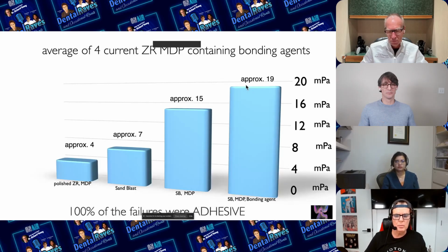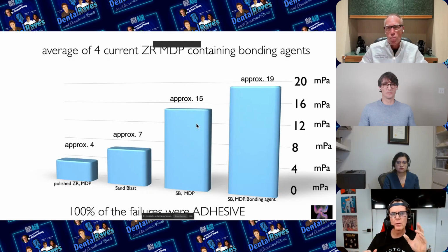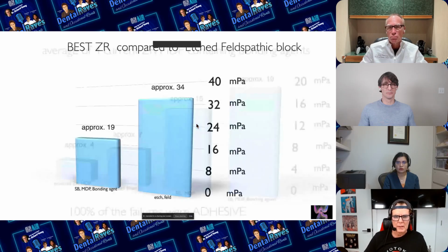All right, so now here's the super interesting thing: it was 100%. Every one of those, all 4 materials, it was 100% failure, adhesive failures. So in other words, it just pulled the bonding agent off. Now, Anvita, I do need to get you these specimens, and we'll work on that, because clearly if we look at it in an SEM, we might see a little thin layer of resin. Okay, but visually and under a microscope, I didn't see anything but zirconia, maybe a little tag or 2 of resin. All right, now, great.